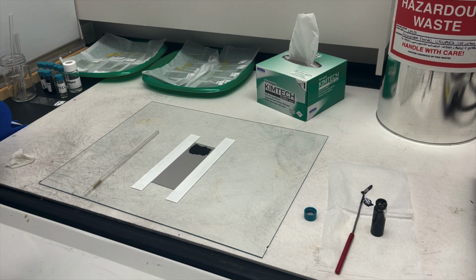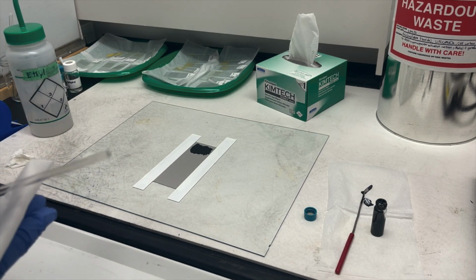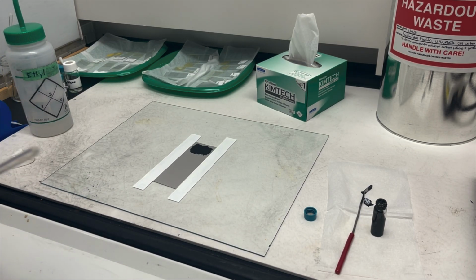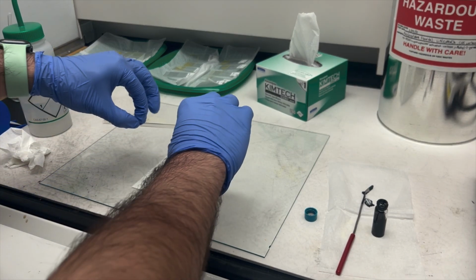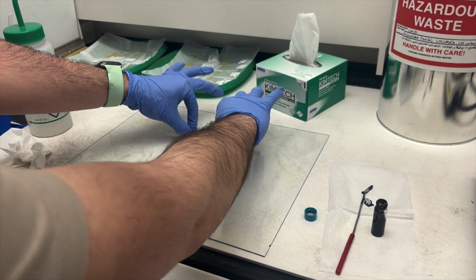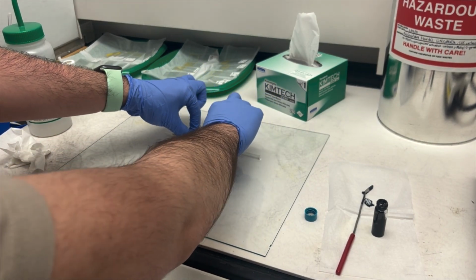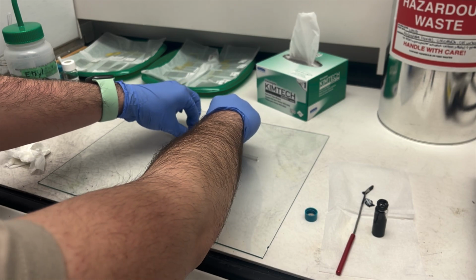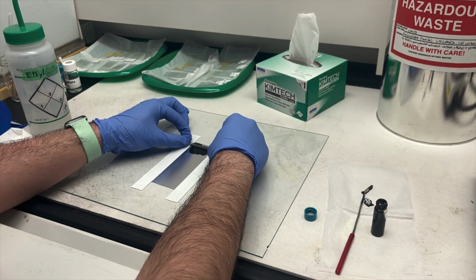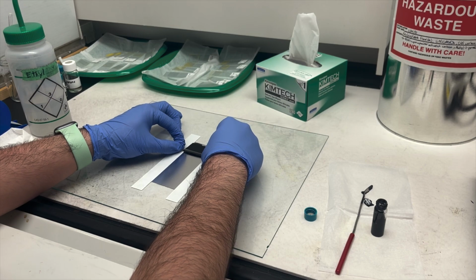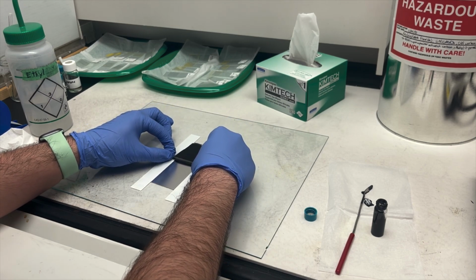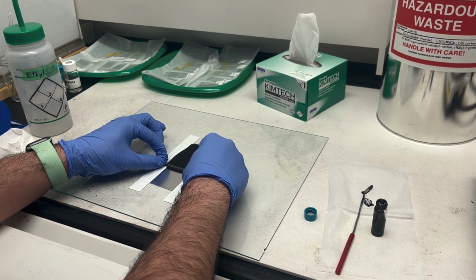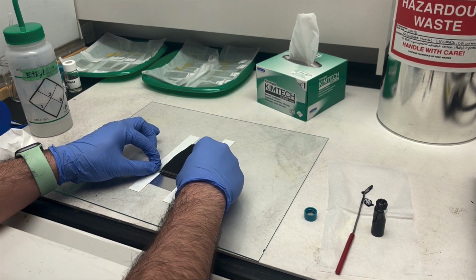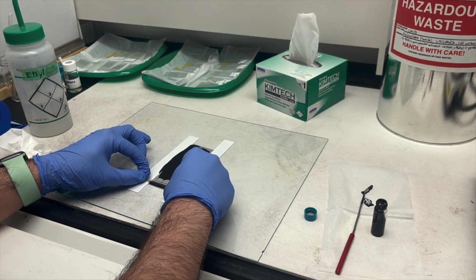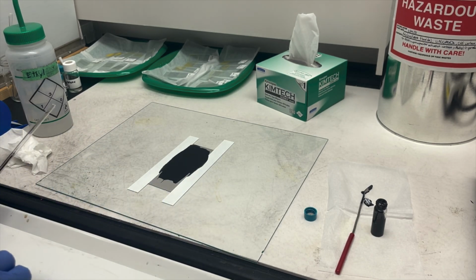We're going to clean the rod with an ethanol-soaked Kim wipe so as to remove any rough particles on its surface. Then, holding the rod with the tips of your fingers like so, and your palm well above the rod with elbows raised, you will slowly pull the rod towards you in a smooth and continuous motion, with your fingertips gently pressing the rod into the tape as you pull. This should be done no more than twice, and ideally is done only once.